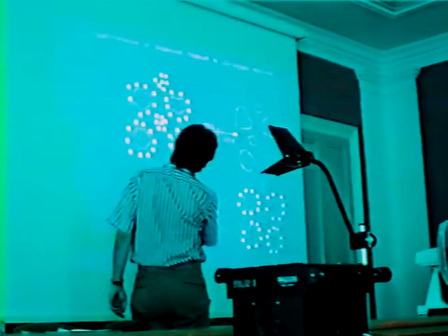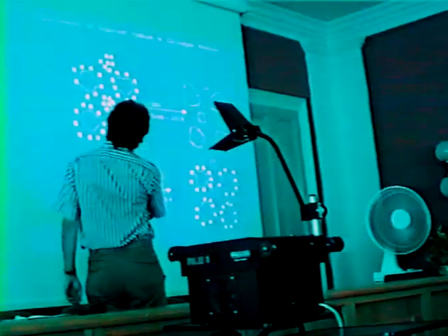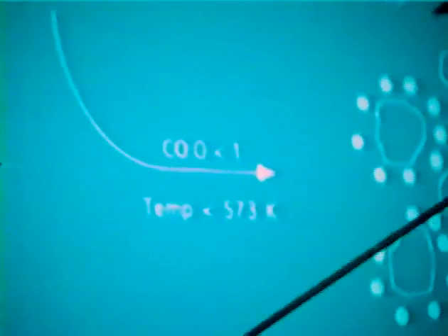However, when we carry this out in an excess of CO, then the dicarbonyl species can no longer agglomerate into the original particle, possibly as a result of oxygen adsorbed at the peripheral atoms. However, where there is an agglomeration or a cluster of dicarbonyl species within close enough proximity, these sites come together to form these small crystallites, which I showed, which resulted in the small band we see at about 1905 wave numbers. Can I have the next slide?